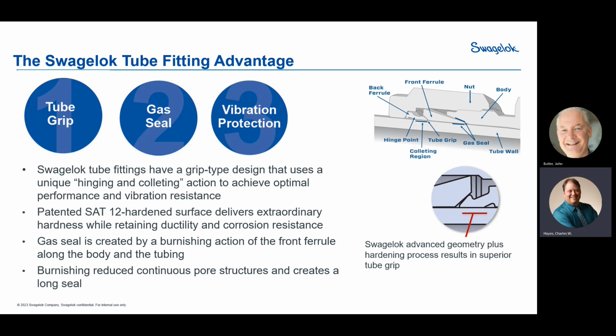Burnishing allows you to knock off the high points, fill in the low points with the material, plastically deform them, move them along without galling or welding them together. And that is the way in which we are able to get that very, very fine finish burnished along that area, reducing continuous pore structures and getting a long seal. So that's the front ferrule and how it works.